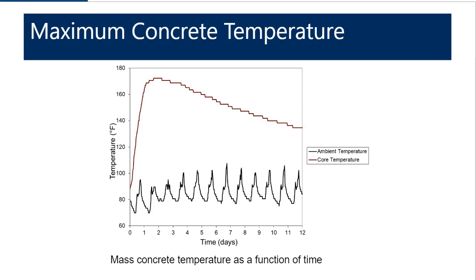And so they installed temperature sensors into the mass element. And what happened is the contractor, per the plans and specifications, was able to maintain a placement temperature of under 90 degrees Fahrenheit. However, for that particular mix, the maximum temperature ended up going up to over 172 degrees Fahrenheit. And so the specs did say that the core temperature needed to be 160. And so then there became a dispute about whose responsibility it was, because the concrete temperature exceeded 160 degrees Fahrenheit.